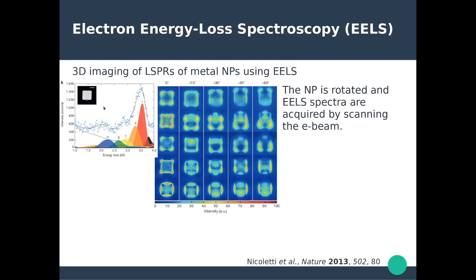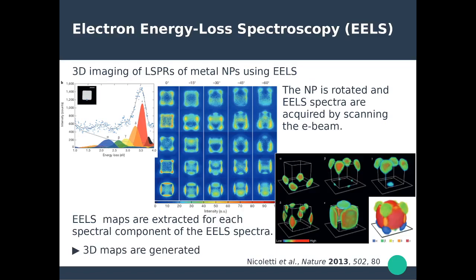What can be done to extend this to 3D is to tilt the sample holder where the nanoparticle sits by a small amount and retake an additional scan to generate another image. So you rotate the sample holder by 15, 30, 45, or 60 degrees, generating successively different two-dimensional maps representative of the plasmon resonances at each rotation angle. You can then generate a tomography — a three-dimensional map — from those different snapshots, which is very powerful because it allows you to have a three-dimensional image of the localized surface plasmon resonances.